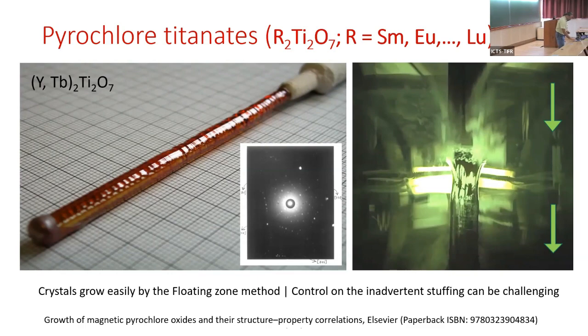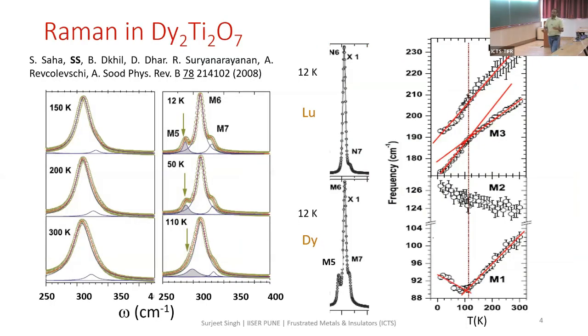Now, the reason why I showed you titanates: I already told you that about a decade back, we did most of these pyrochlores, and our interest was in looking at their phononic properties. Most of these pyrochlores show strong phonon anharmonicity. Here I've taken the example of one of the most extensively studied titanate members, dysprosium 2 titanium 2 oxygen 7 (Dy2Ti2O7), which is a spin ice ground state.